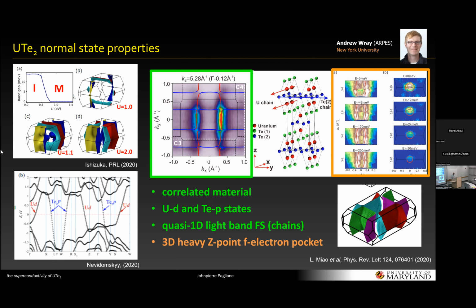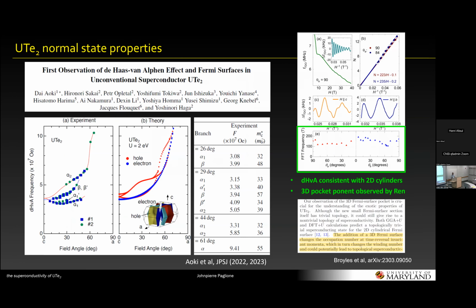Sorry, I forget about this particular one. I'll show another band structure later, but this is probably a calculation that uses a sort of thorium-like atom, so there's inherently no F states. And the masses from the quantum oscillations, are they sufficiently heavy? Yeah, they're right here. These are from the Lifshitz-Kosevich fits. These are 40, 50, 60 masses, and there's also a bit of a debate as to whether that completely accounts for the measured heat capacity or not, but it's pretty close.